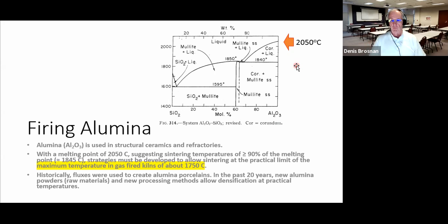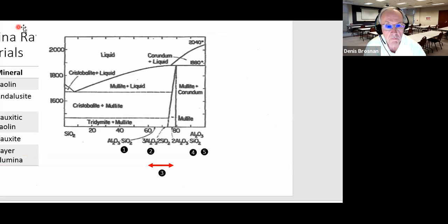Now, historically, because of these melting relationships and furnace capabilities, we added silica to make what you might call alumina porcelains. And that was because the raw materials that we had, in terms of coarse alumina sources, which we'll call tabular alumina, fine alumina sources, which we'll call calcined alumina, and other additives that go into the mixture, we could make products at 1750 with a little bit of liquid phase. Now, of course, today we have more reactive aluminas, different calcines and different particle size distributions. So we're able to make 99% alumina structural ceramics in fine particle gradations that meet density and strength requirements.